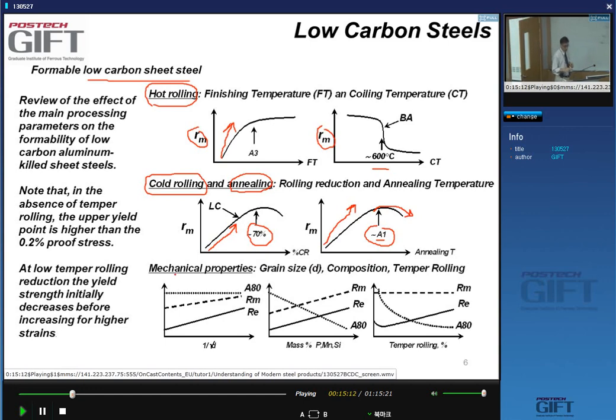The mechanical properties are a function of the grain size and of the composition. Obviously, you know what the effect is of the grain size on the strength. You know what the effect is of phosphorus, manganese, and silicon on the strength. These are solid solution hardeners. And you also know that temper rolling has an effect on the properties. Maybe we can have a look at the effect of temper rolling on the properties, so you understand this graph a little better.